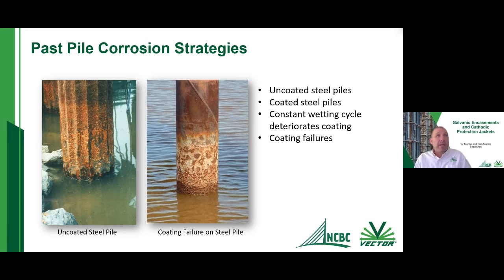But what ends up happening is you end up getting coating failures, right? So whether it's from holidays when the coating was applied, or during installation. During installation, obviously the sheet pile or these pipe piles can be damaged just through the driving operations, and also just bringing them out to site. So you get these coating failures, and then you get this corrosion that occurs.